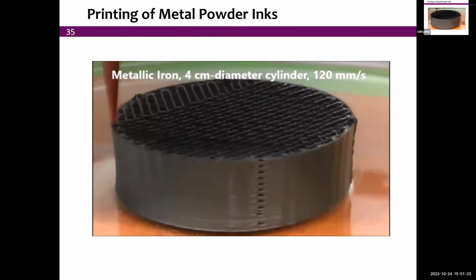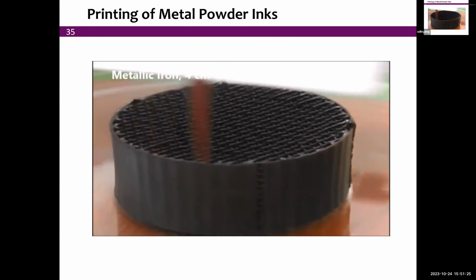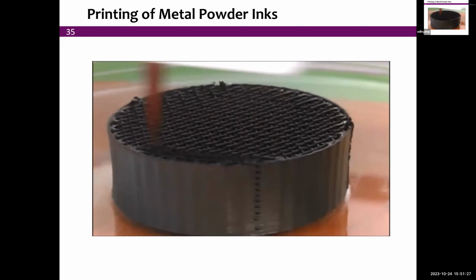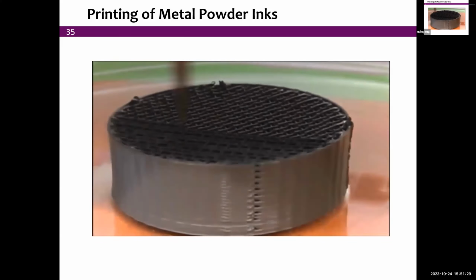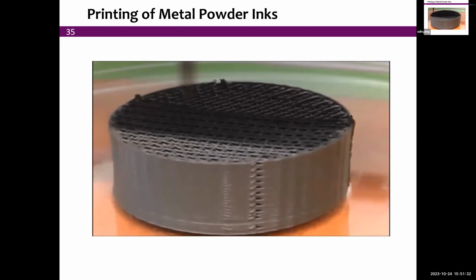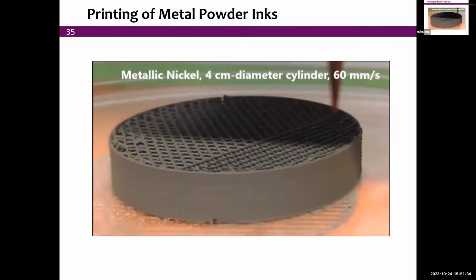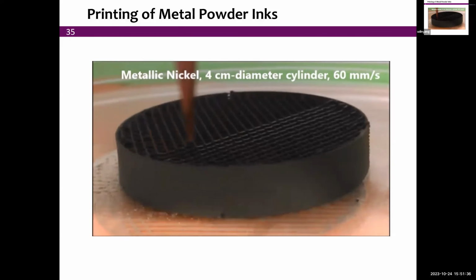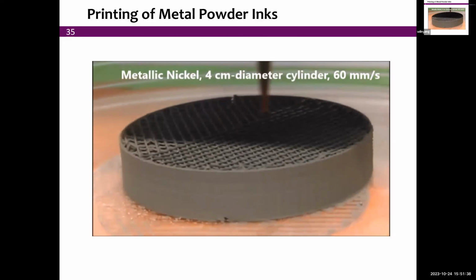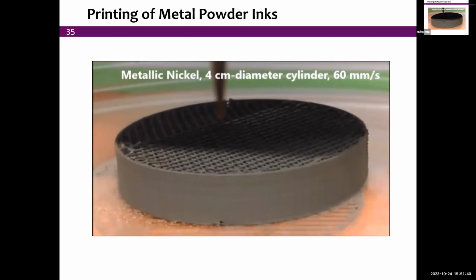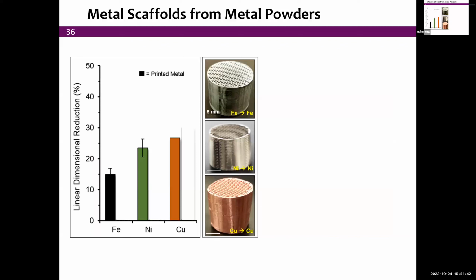So far I showed you the case where we use oxide particles. Now we can also do it with metallic particles, albeit those are going to be larger particles, because otherwise, if they are super fine, they will catch on fire. So here are metallic nickel particles, which may be 10 microns in diameter or so. And we see that we end up with perfectly fine and nice metallic structures. We have to be a bit more careful now about the binder during decomposition,